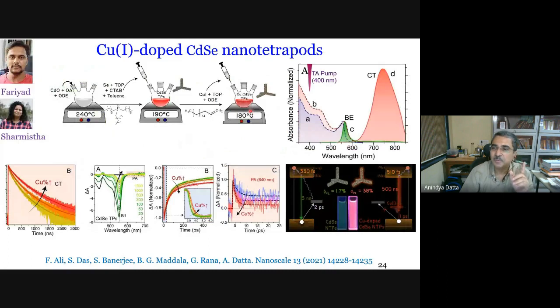And we were very happy to note that these tetrapods had a very strong what is called charge transfer, CT, emission. It is copper 1. It is doped with Cu1, which has been established by Faryad by titration with a hole scavenger as well. So very strong CT emission, associated with a lifetime of hundreds of nanoseconds. Why does that happen? By a careful analysis of transient absorption data in different ranges, this is the scheme that we came up with.